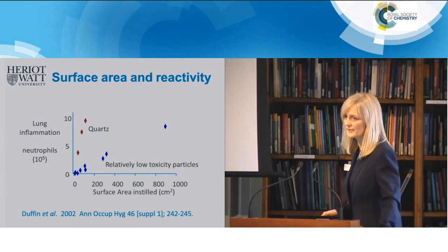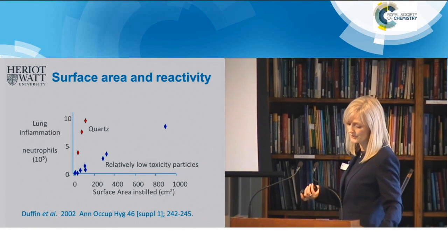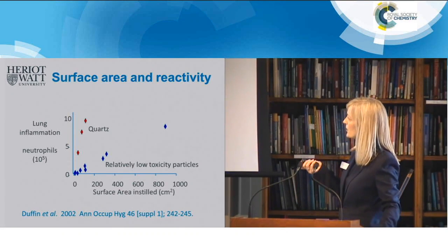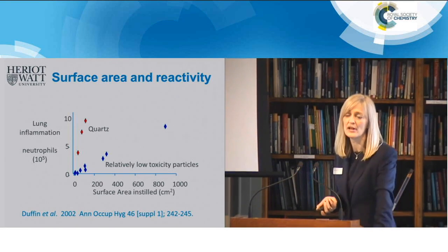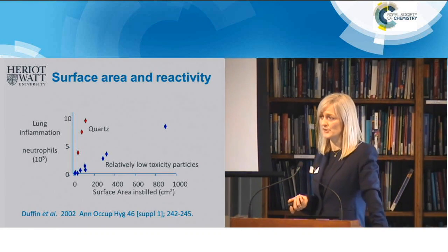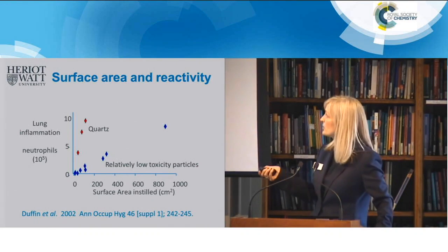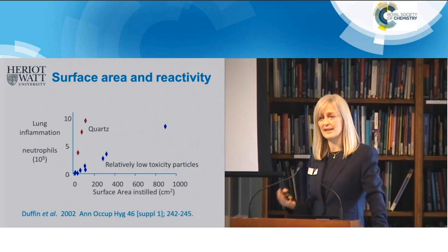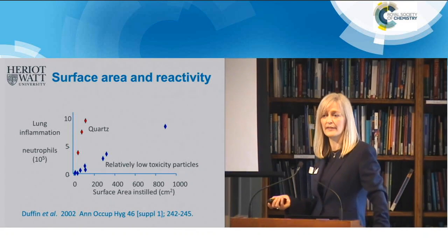So some work conducted by one of our PhD students at the time, Roger Duffin, who's now at Edinburgh University, showed that there was a good straight line relationship between the surface area dose of low solubility, low toxicity materials and their ability to induce inflammation. So this includes things like carbon, titanium dioxide, and polystyrene beads.